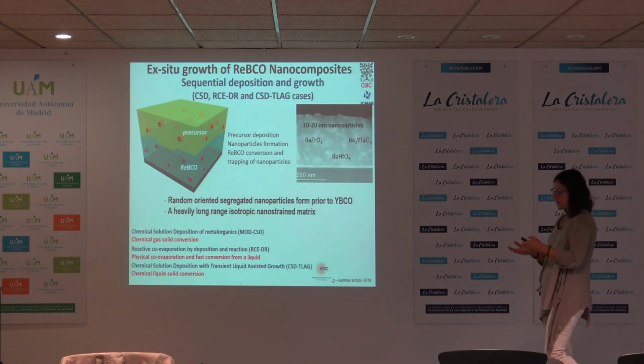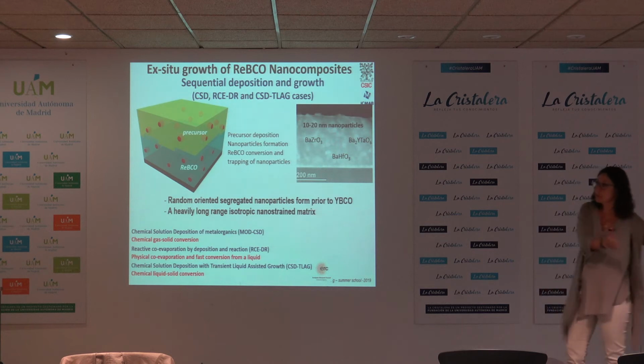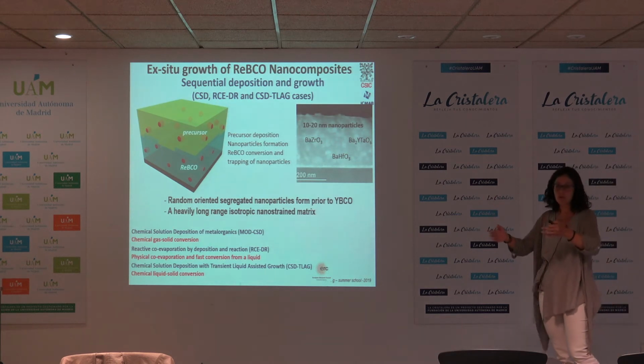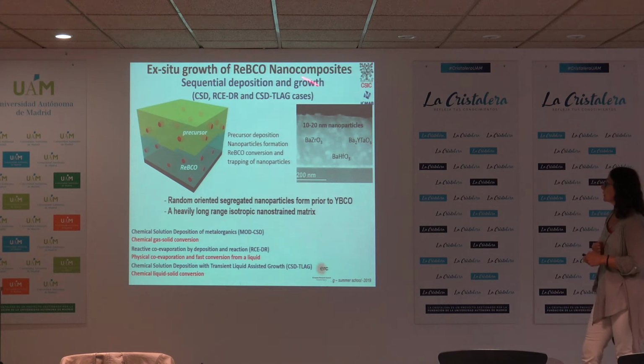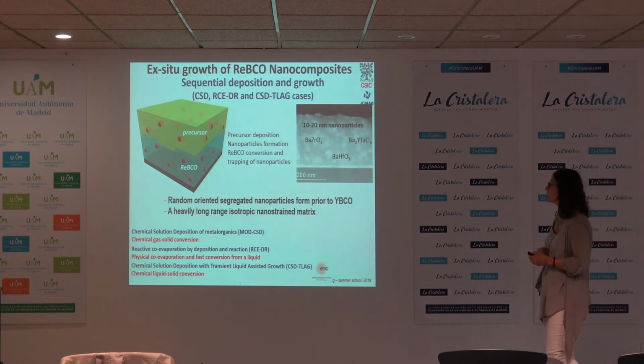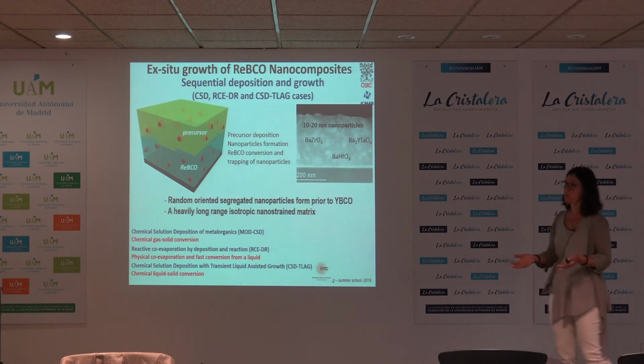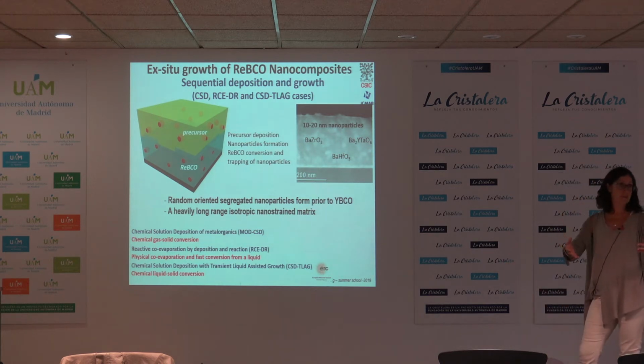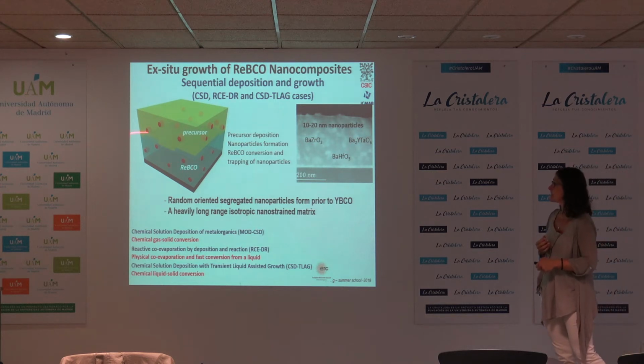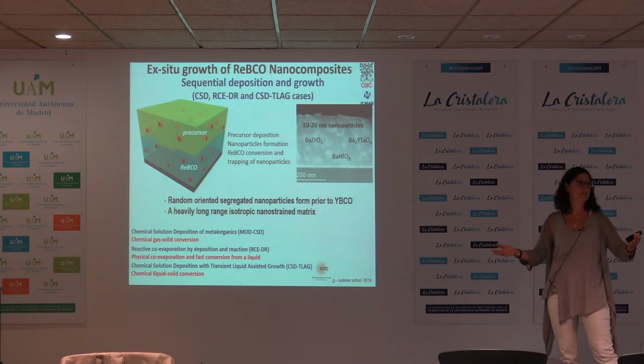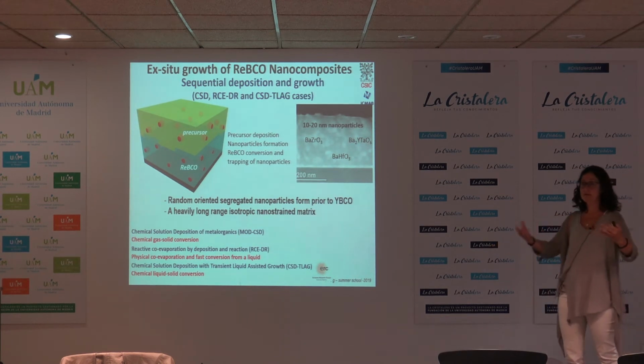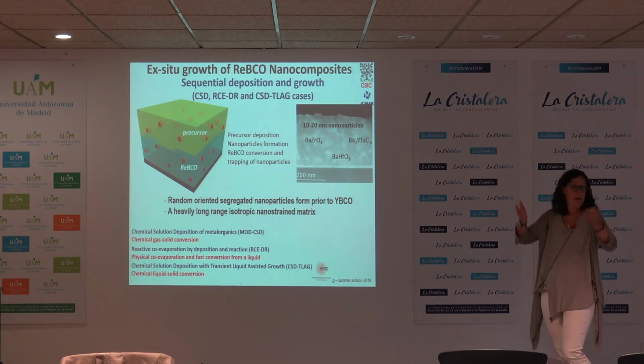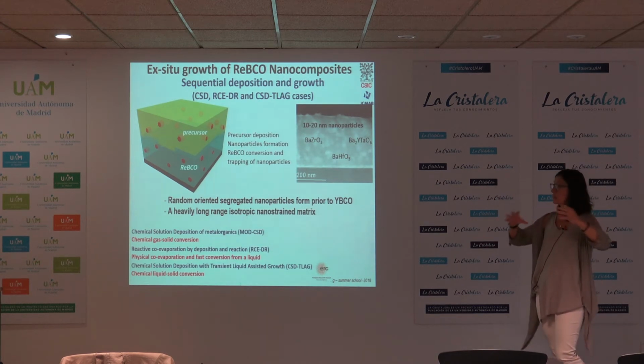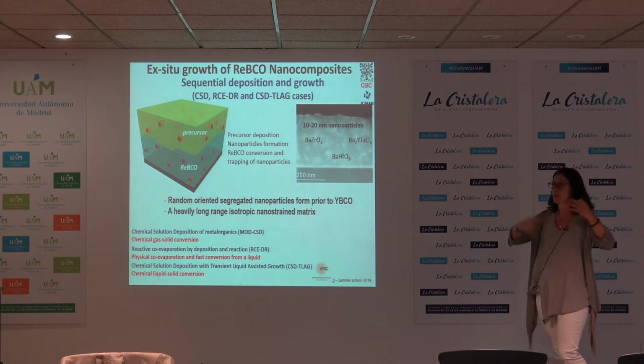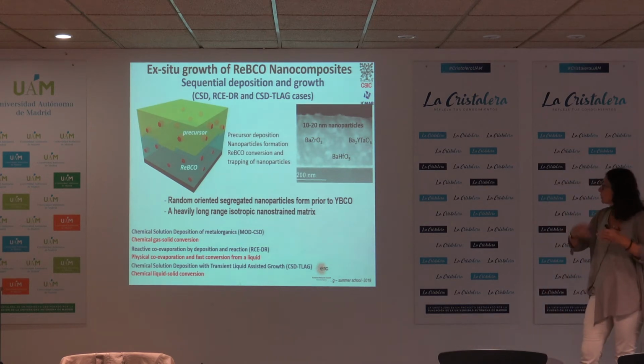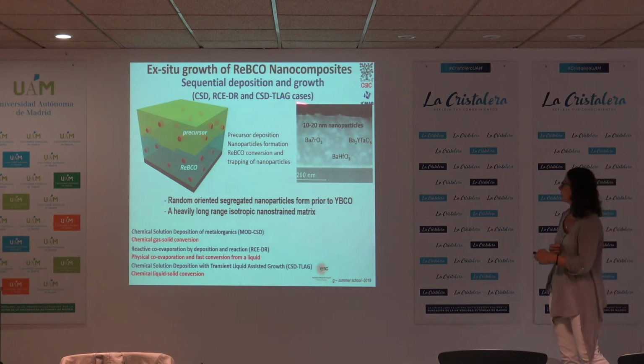If you go to other growth processes, like the one in which we first deposit the precursor phase and then we grow the YBCO, so we first deposit and then grow. This would be the case of chemical solution deposition, for example. In that case, when you want to form a nanocomposite, you also deposit both phases, but the nanoparticles will segregate before, into the intermediate phase, and therefore they will be formed. And then when YBCO forms, it will encounter the nanoparticles. It will encapsulate these nanoparticles, and therefore these nanoparticles will not be epitaxially grown. So we have randomly oriented nanoparticles in a YBCO epitaxial matrix.